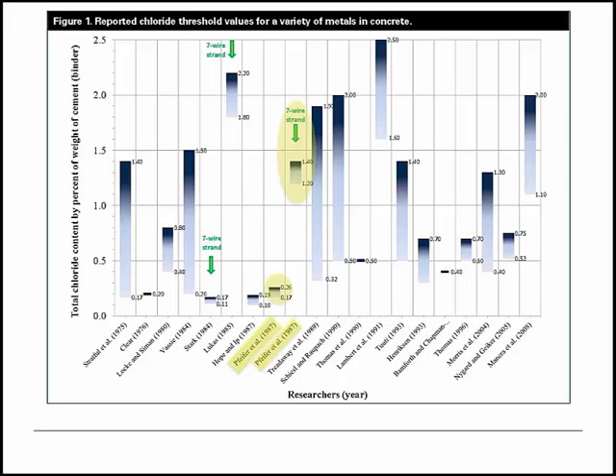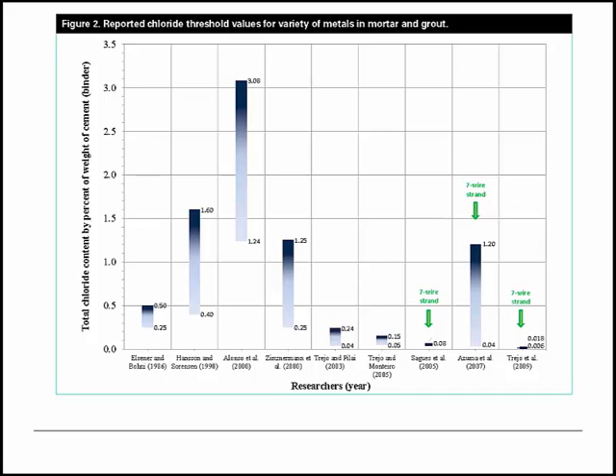And those results are not too different from what other researchers have reported, although some have found the chloride content threshold for strand to be as high as 2.2. Others have found it to be as low as 0.17. And in general, there's numbers all over the board for what is the chloride content threshold. As I mentioned, there's much less available information for strand or reinforcing steel in grout. And this graph was also put together by Federal Highway and reflects that collection of data that's available from 1986 through 2009. As you can see, some of the more recent research suggests that strand in grout may have a chloride threshold of even less than 0.01. The most recent work, done by David Trejo, found 0.006 to 0.018, which is well within PTI's specified limits. Others have found it may be as high as 3.08.